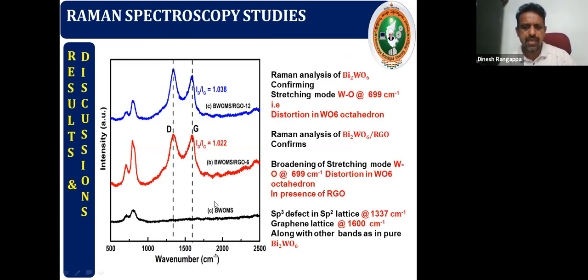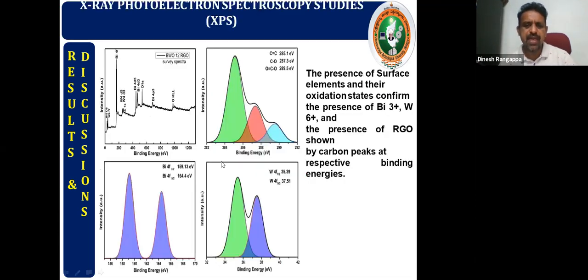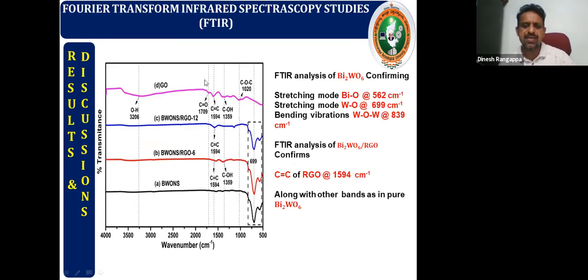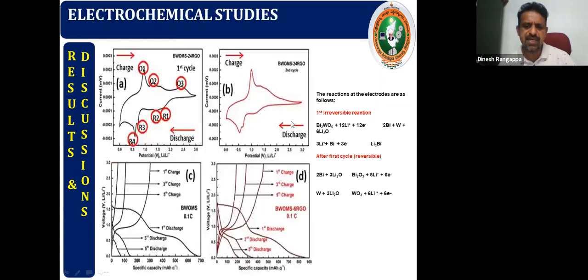So again, Raman confirms the presence of RGO, that is 6 to 12% RGO, which is completely wrapping the bismuth tungstate. And the pure phase of bismuth 3+ and tungsten 6+, along with the presence of RGO, was confirmed by XPS measurement without any other impurities. And surface functionality was studied again with FTIR and confirmed the presence of surface carbon-carbon bonds and carbon-oxygen and other surface functional groups.